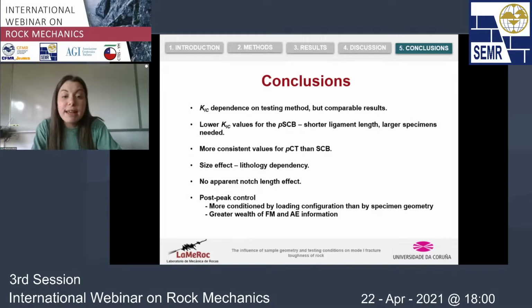We have also seen that the values of fracture toughness were more consistent for the PCT than for the SCB, and that there was a size effect, but that it was really dependent on the lithology that we were testing, and that there was no apparent effect of the notch length, even though the graphs were suggesting it. And the post-peak control is more conditioned by the loading configuration than by the specimen geometry. And thanks to having this control on the propagation of the crack, we can have a greater wealth of fracture mechanics and acoustic emission information.